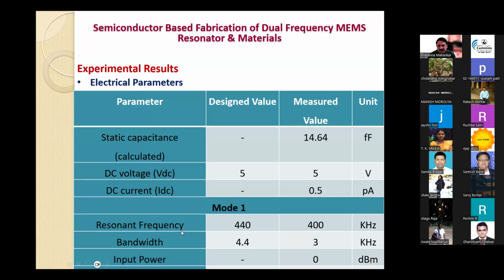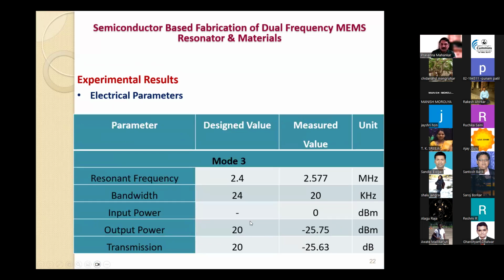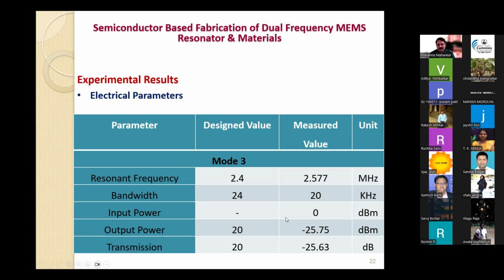The designed value for resonant frequency mode 1 was 440 kilohertz, and we measured 400 kilohertz. It was designed for a bandwidth of 4.4 kilohertz, but we got 3 kilohertz. In mode 3, the designed value was 2.4 megahertz and the measured value was 2.5 megahertz, with bandwidths of 24 and 20 kilohertz respectively. Output power and transmission loss, these electrical parameters, have been given in the table.